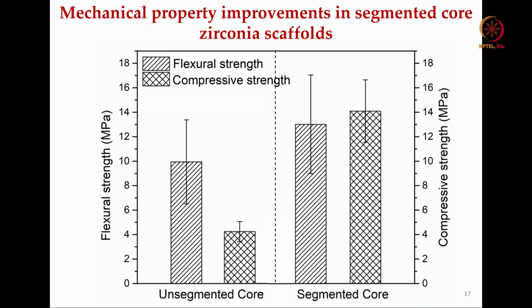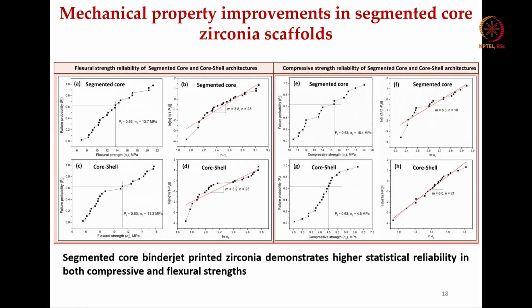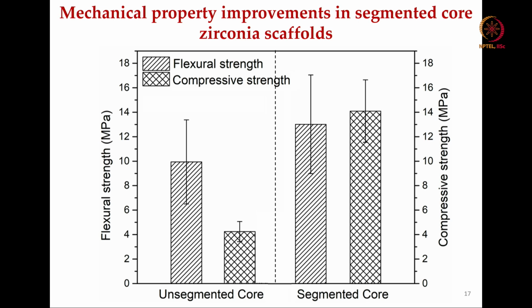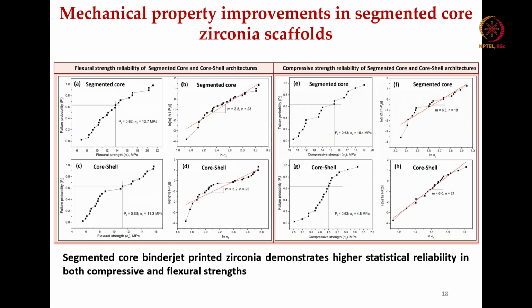I am not going into more details, but a similar methodology was used to measure the flexural strength and compressive strength. In the unsegmented core region, the flexural strength was 10 megapascal, and it increases to 12 or 12.5 or something. Compression strength is increased much more significantly. It was like 4 megapascal, and it has gone up to 14 megapascal, more than 3 times the compression strength after the CAD file based modifications were done. So, there are CAD file based modifications, and there is also modification in the infiltration stage, both of which synergistically impact and improve the strength properties of the zirconia.